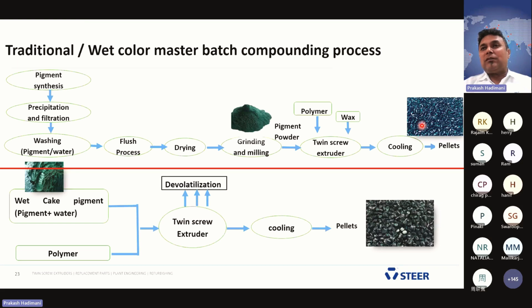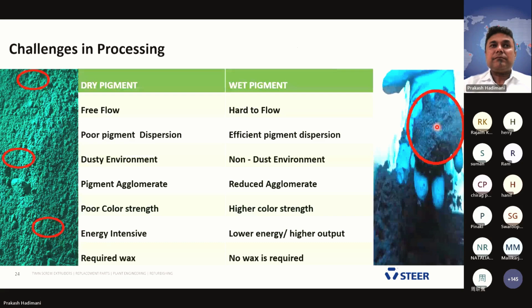But if you compare the pellets of the dry pigment color masterbatch and the wet pigment one, there is a lot of difference. The dispersion value is almost two times better than your traditional dry pigment compound. Here, on the left-hand side, if you see dry pigments, there are agglomerate particles. And in the wet pigment, we didn't find any agglomerate particles. It had already water in it.